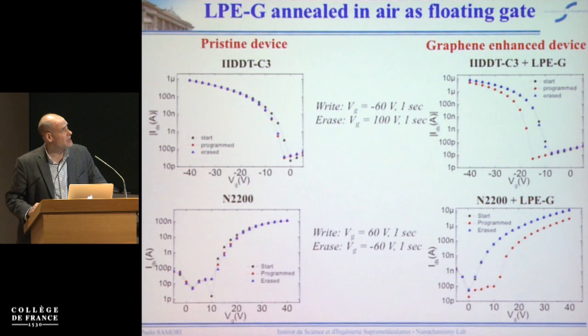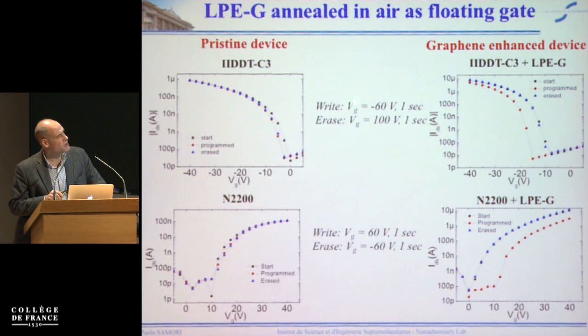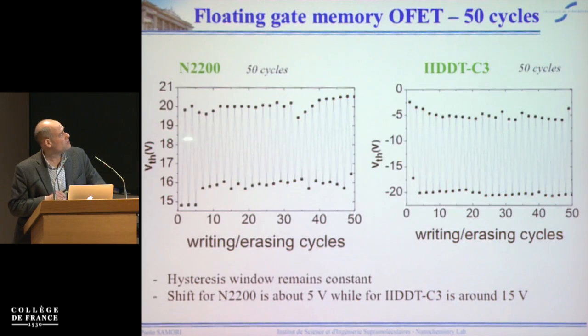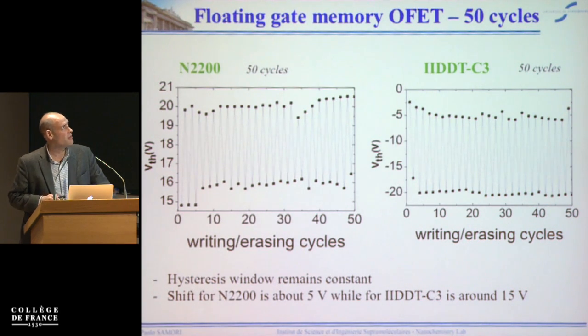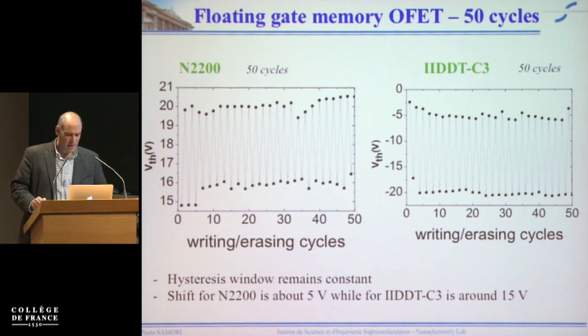Now, what happened is that we realized that by applying voltage to the gate electrode, we are doing nothing else than charging and discharging our graphene patches. And so you can see that we can write the information by applying a negative voltage to the gate electrode and erase by applying a positive voltage to the gate electrode. Likewise, you can do this with different types of organic semiconductor, P and N type. So you can essentially sweep the threshold voltage in this way just by applying voltage to the gate electrode. And so this is nothing else than a floating gate memory. And you can make over 50 cycles with very little fatigue.